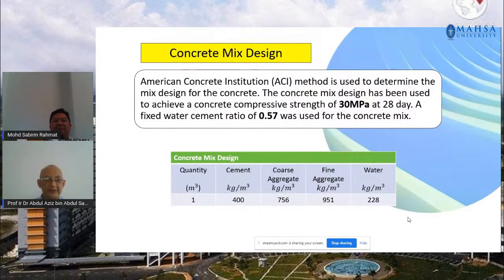Now the concrete mix design is based on the American Concrete Institute, ACI, and the target concrete strength is about 30 megapascal at 28 days. So this is our target strength, 30 megapascal at 28 days. The water cement ratio selected was 0.57.